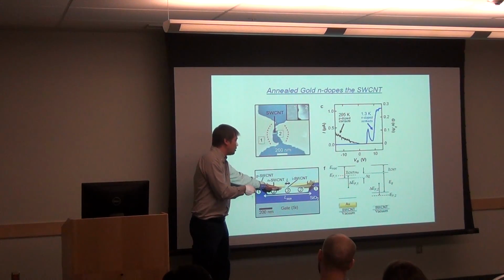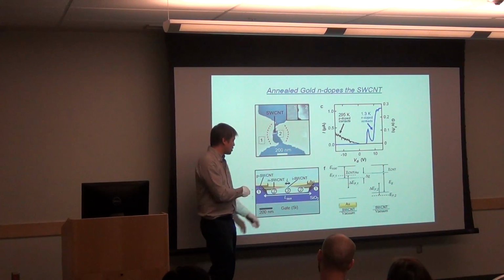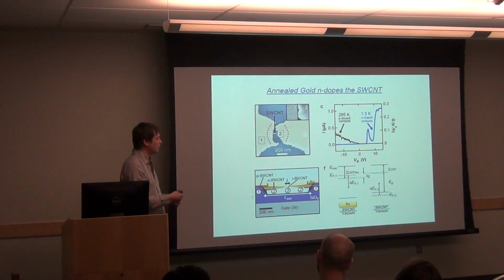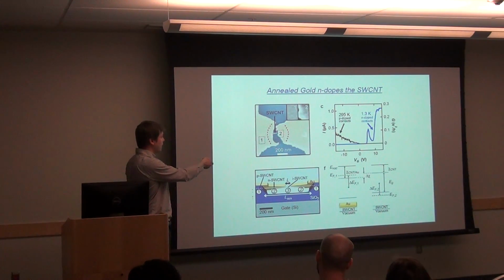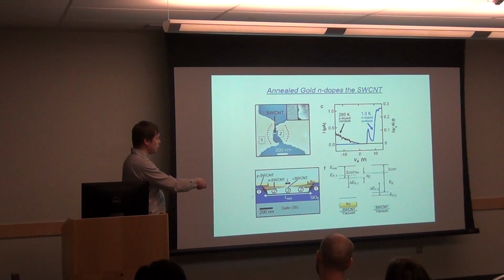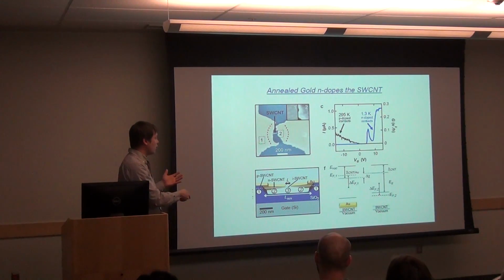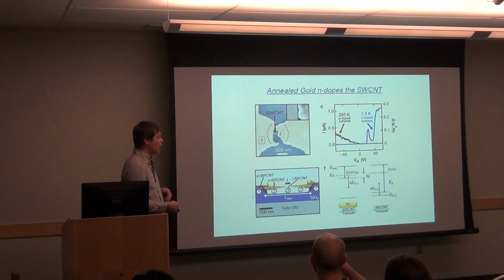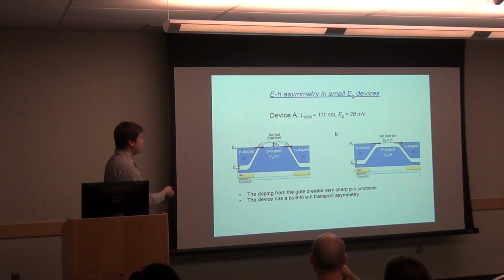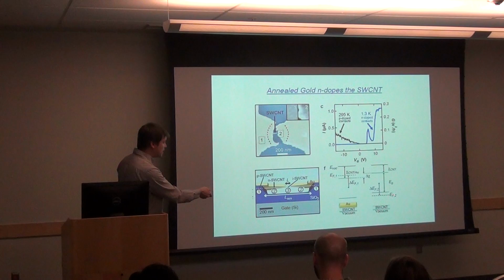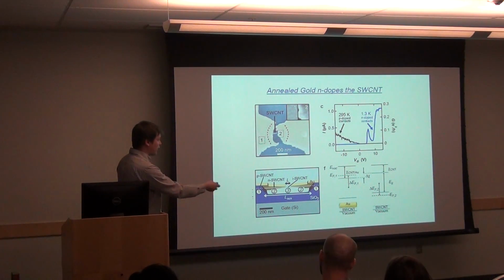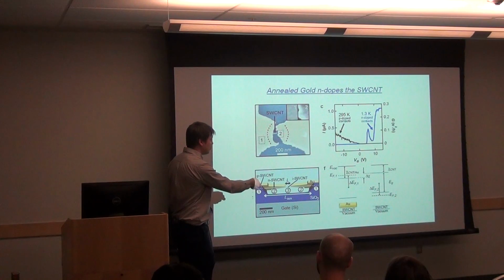But the actual value of that position depends on how much oxygen is in the gold film. When we do this electromigration to open up the gap, it turns out that we bake the gold and remove the oxygen, and it usually makes it N-doping. If you then add oxygen by warming up the system, you can also make these regions P-doping. So we know we can control how much doping we have in the contacts of the channel. Depending on where the bands are, when these two sections touch, the Fermi level will have to align, and you might get either a barrier forming between the two or not.